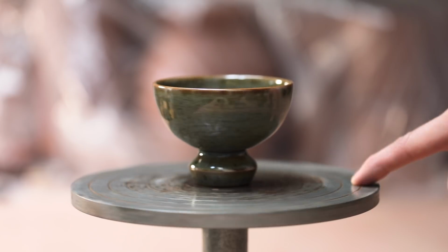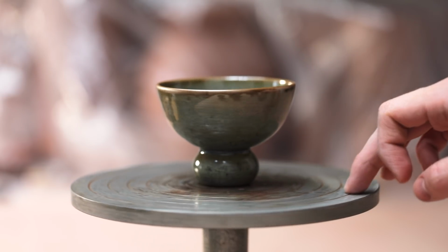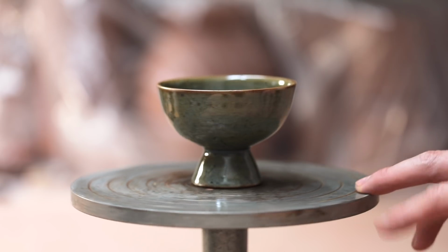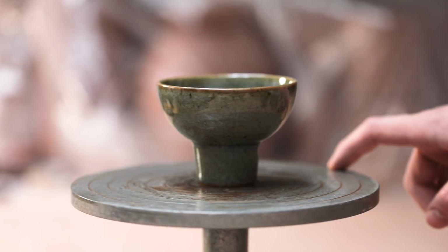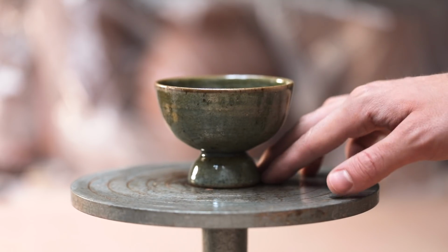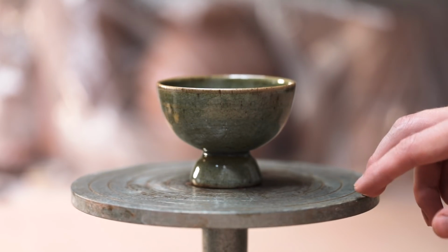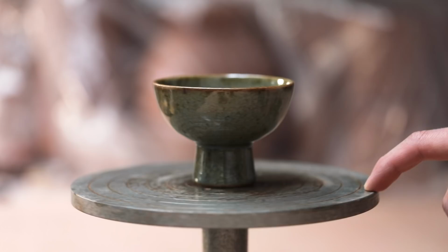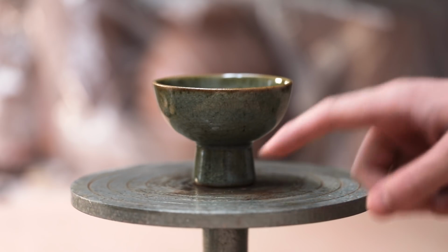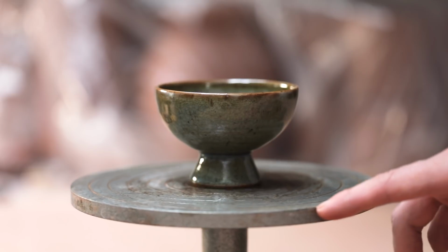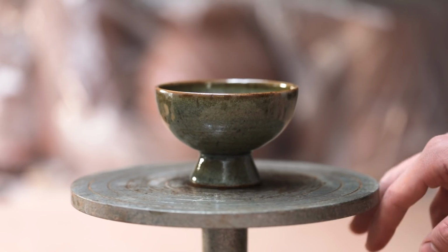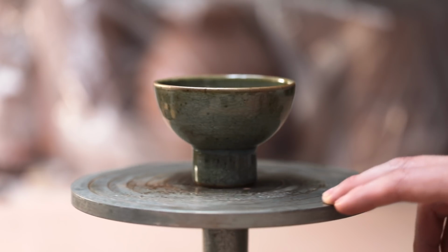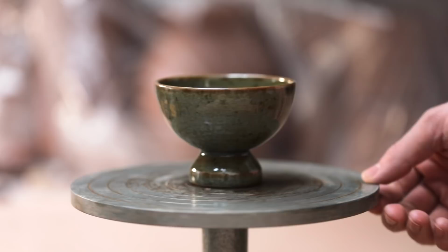And here they are, the finished pieces. The feldspathic crackle glaze has sort of softened the forms in some cases. It's also broken away from the rim, revealing the lovely iron-rich clay beneath, which is turned almost metallic and iridescent in some cases. Some of the shapes definitely worked more than others, but even with these differences, when displayed together or in a row, they do work, and with this initial batch tried and tested, I think the next lot will be far better.